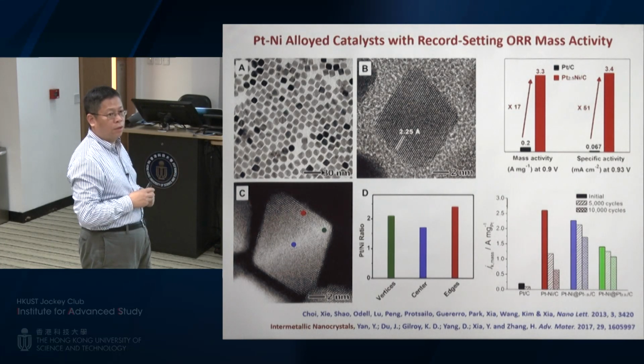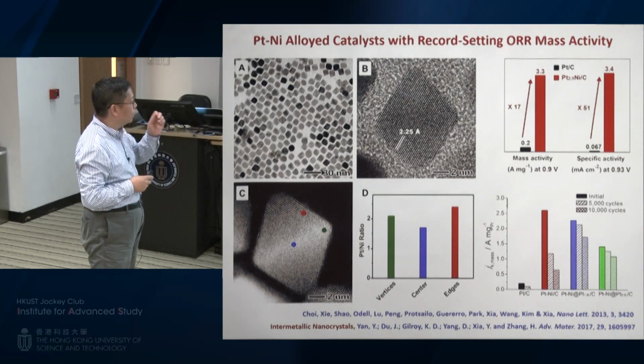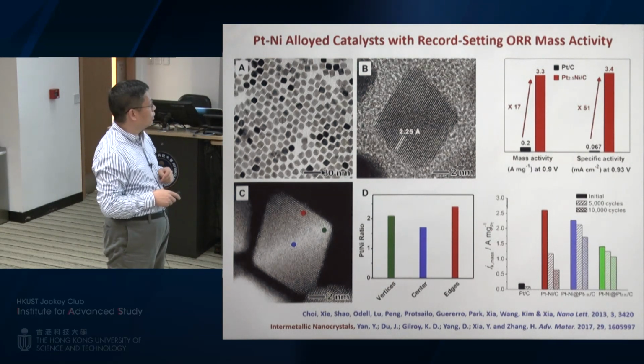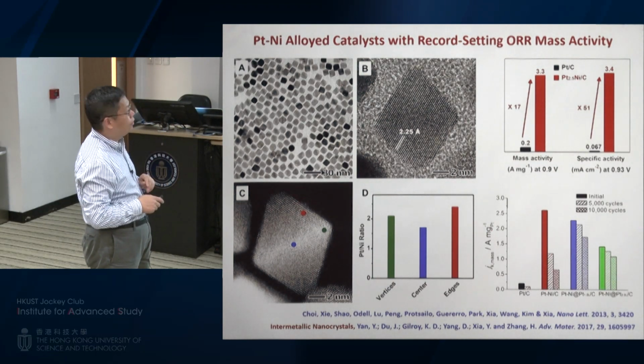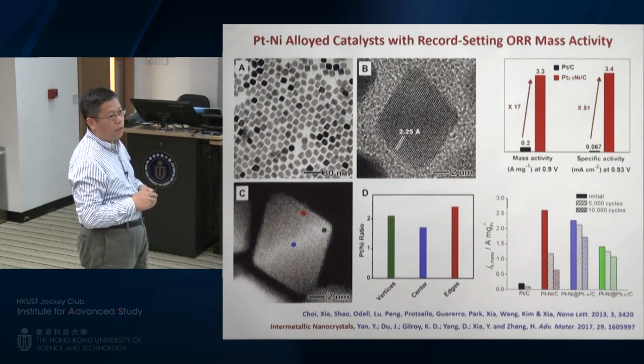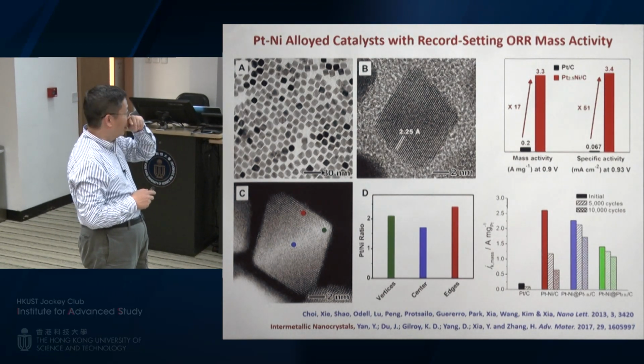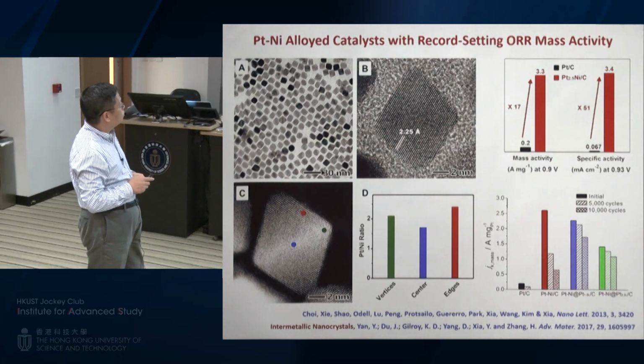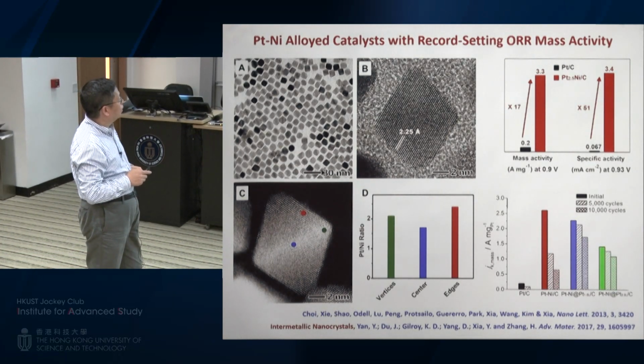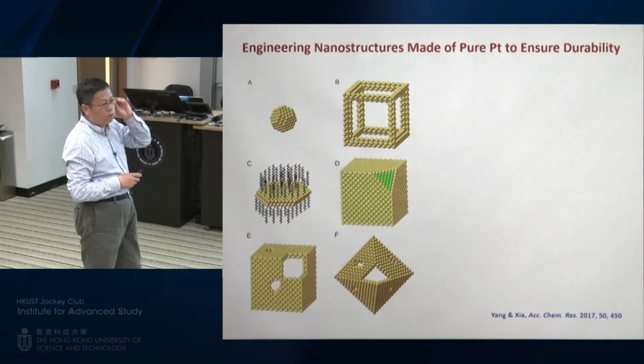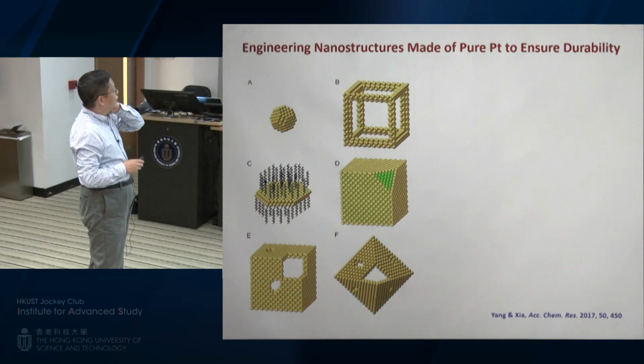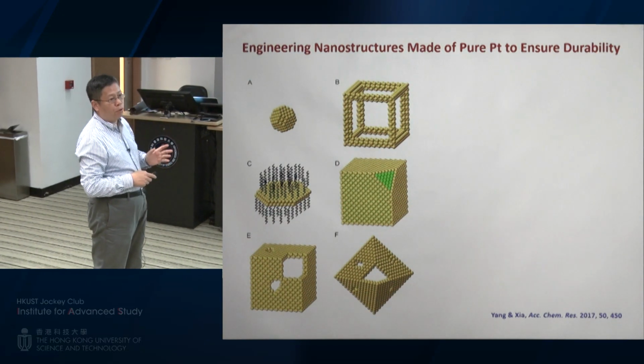It's an ordered structure. So that could be one way actually, but it's still impossible. It has been very challenging to make Pt3Ni intermetallic octahedra, so it's still challenging to accomplish that. That's why we switched to a different system when we started to work with Toyota a few years ago, 2 years ago. So in this case, we come back to pure platinum.